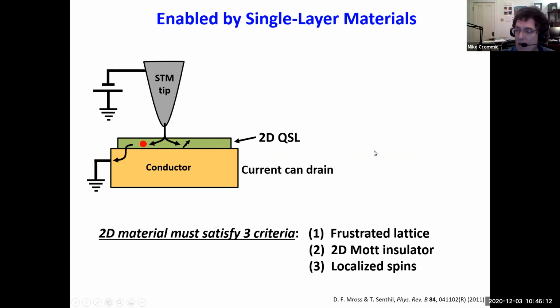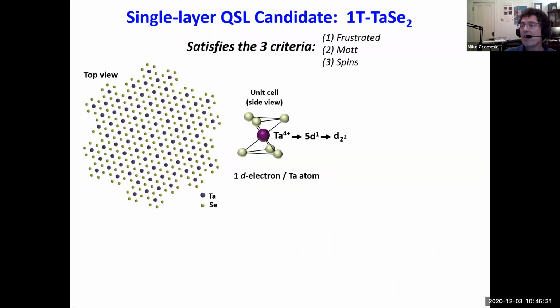But this two-dimensional quantum spin liquid is very special. You need a very special material to give you a two-dimensional quantum spin liquid. For example, the minimum criteria that it must satisfy is it has to have a frustrated lattice, it has to be a two-dimensional Mott insulator, and it has to have localized spins. And so what I want to do now is introduce you to this relatively new material, single layer 1T-TaSe2, which we believe satisfies these three criteria and which actually gives us a quantum spin liquid.